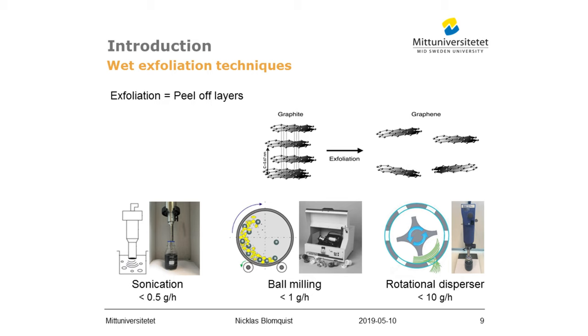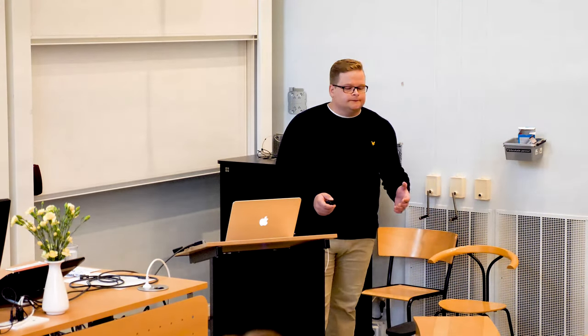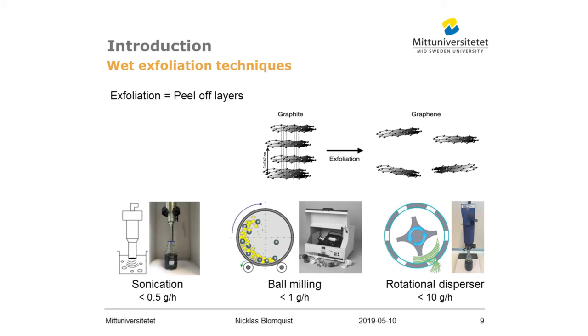This can be done both in dry and wet state. And sonication is the standard laboratory procedure to do this. But sonication is low scale, it's time consuming, and the energy efficiency is really low. Other approaches are ball milling, rotary dispersers, and several more. Rotary dispersers and jet milling are seen as the state of the art today when it comes to scale, with a production rate of about 10 grams per hour or less.